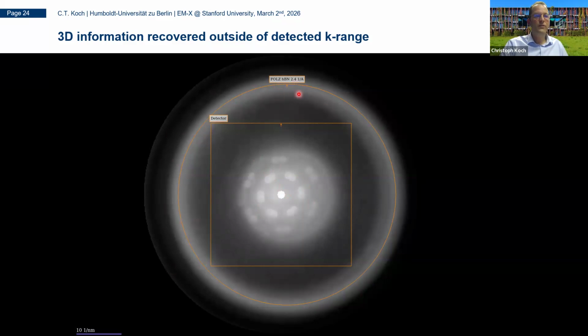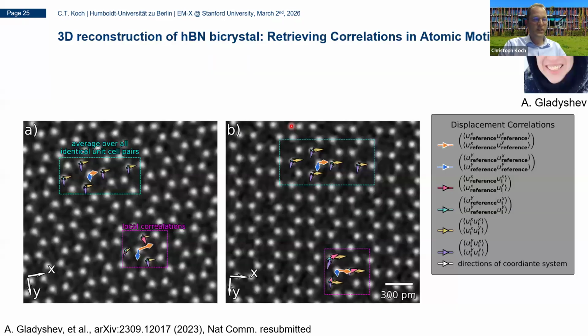Right, this corresponds exactly to the first order Laue zone of hBN, which has a c lattice constant of 6.6 angstroms, and then at 60 kV, which was the voltage that this experiment was carried out on, you have these 2.9 inverse angstrom spacing, which is outside the detected range. So interestingly, multi-slice reconstructions actually allow you to recover diffraction information which is outside your detector range, because these high scattering angles were not even recorded in the diffraction pattern. And then from these data, this is now the top slice. This is now the lattice from the top half of the crystal. This is the lattice from the bottom half of the crystal.